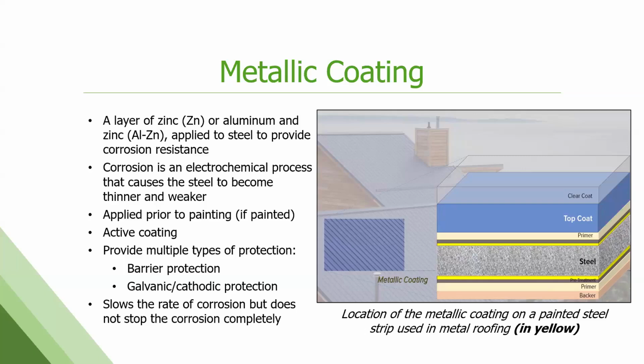Zinc and aluminum is an active and a barrier coating. So the aluminum portion acts as a barrier to corrosion, while the zinc is a sacrificial coating that's going to sacrifice itself to protect the steel. So those two things together in the right ratio give you an incredibly long performance on corrosion. We're talking like 30, 40, 50 years of corrosion protection out in the field.